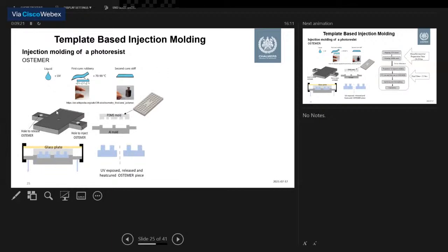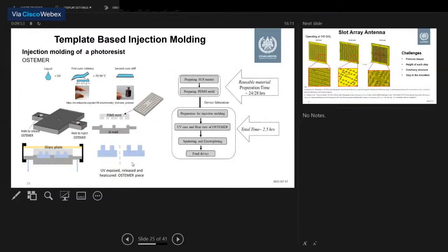For injection molding, we use an aluminium mold. The aluminium mold has two holes. When we place the previously fabricated PDMS mold with this aluminium mold, we press them together with a glass plate and clamp them together. And then when we inject the OSTEMER, we UV cure it and release it, and then after heat curing, we can have this final OSTEMER chip. So this is what the final process steps look like.